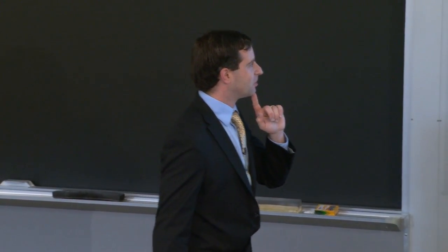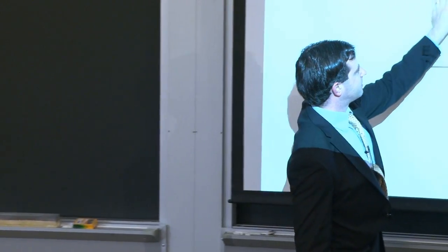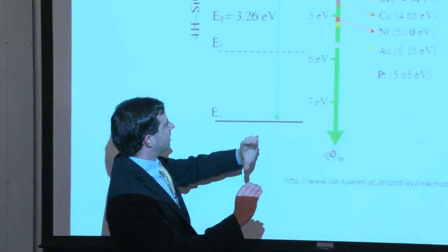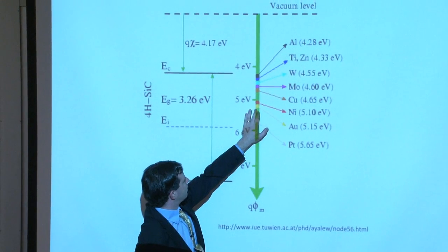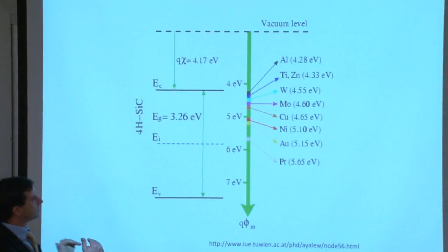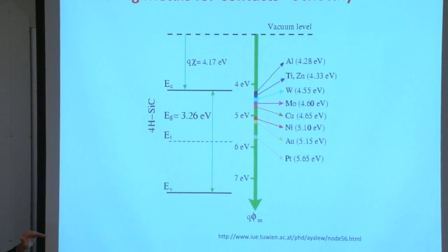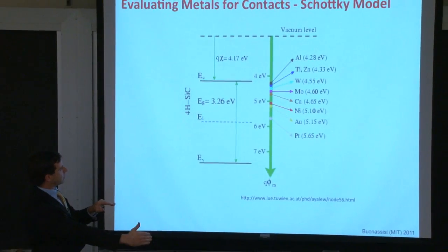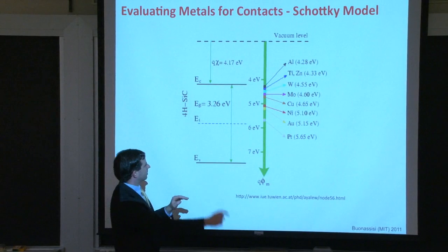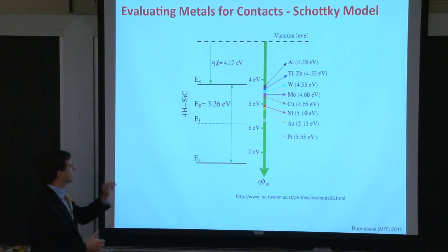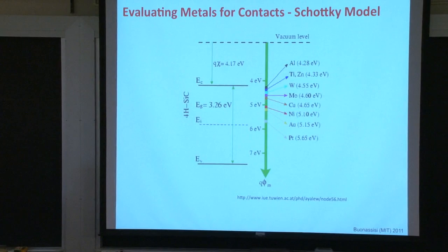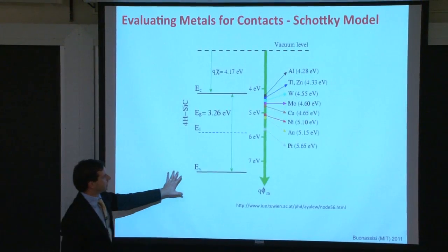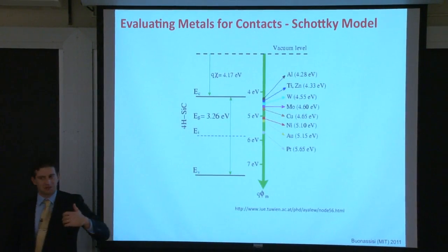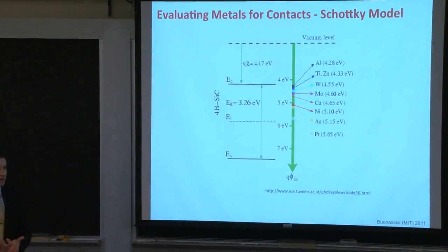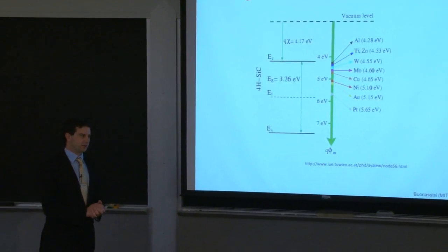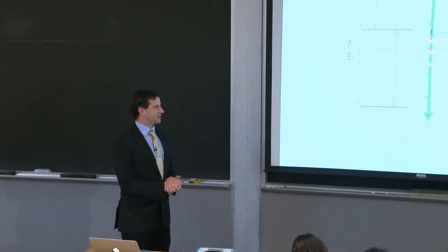Okay, so we have a variety of metals to choose from, almost like a menu. And then the semiconductor here, and we can see, okay, if we make contact, and let's say we pick nickel in this case, if the Fermi energies line up, that means we shift the metal down. That means that our vacuum level is going to fall down here in the semiconductor, and for electrons at least, we'll be very easily contacting this silicon carbide material. So from a simple energy band diagram point of view, we can begin to see which contacts will create ohmic contacts and which contacts will create Schottky contacts. That's in the ideal world.